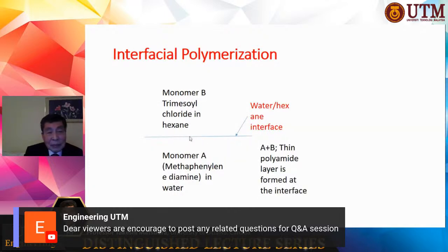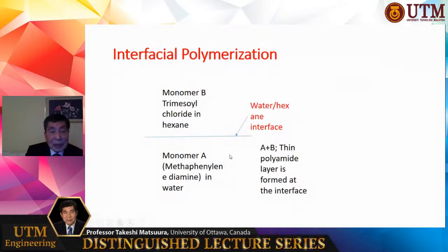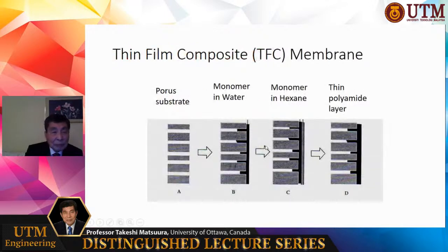Therefore, between hexane and water, there is an interface, and reaction takes place between monomer A and monomer B at the interface, and A plus B, a very, very thin polyamide layer is formed at this interface. And this thin polyamide layer can be used as the membrane. So this is called the interfacial polymerization, and this is a process.